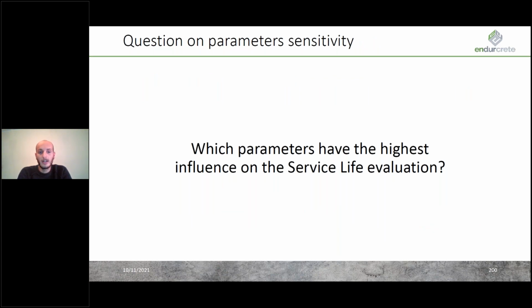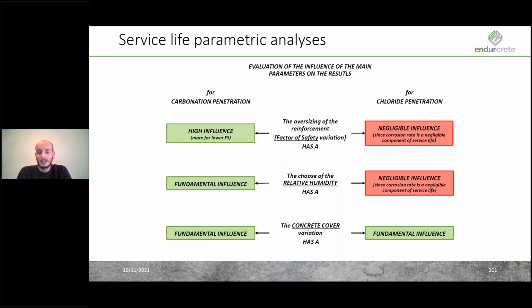The second question that we will have a look at is basically which parameter has the highest influence on the service life evaluation. Basically, here we can see that the most important parameters that have an influence on this evaluation are the factor of safety of the concrete section, the relative humidity related to the environment in which the infrastructure is located, and the concrete cover of the rebar of the section. For the carbonation case, we can see that the influence goes from high to fundamental for all these 3 different